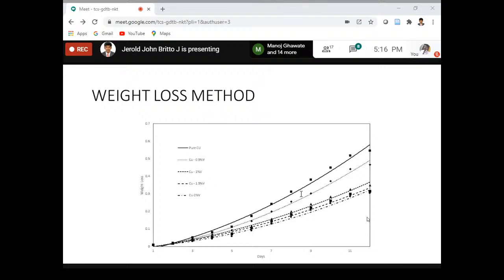So after one day, 24 hours, what is the weight loss? Like that, for 12 days, I have taken the values and I have found that for pure copper, the rate of loss of its weight keeps on increasing. But when vanadium is added to this copper, the weight loss is reduced. That's what I came to a conclusion.